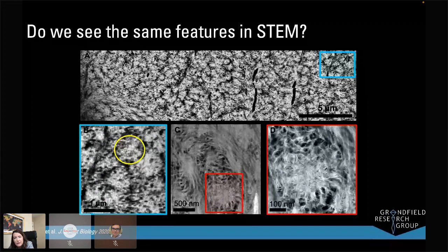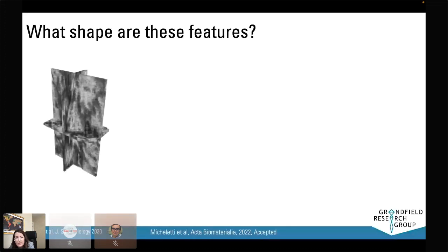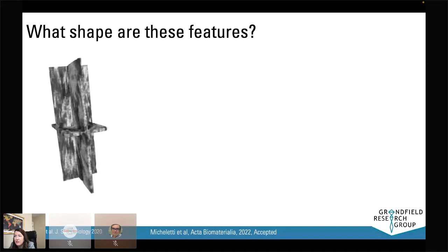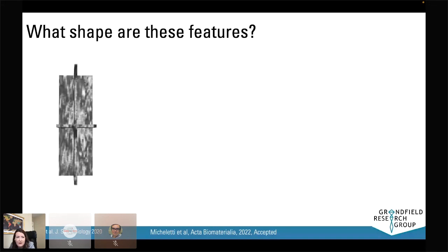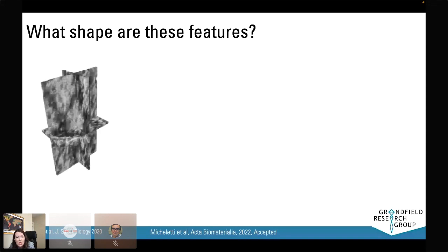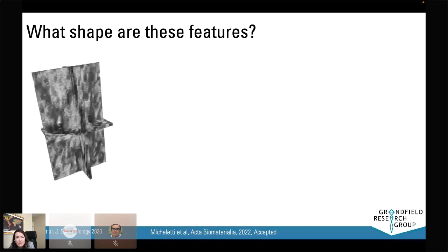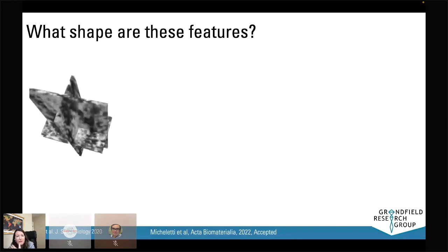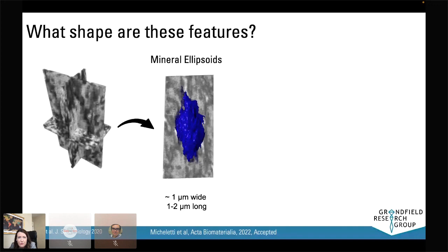So these features appeared circular in the TEM, but now with the plasma FIB, we can explore what shape they actually are. When we look at the three-dimensional shape of these features, we find that they're not just circular. They have a circular cross-section in one direction, but they're actually elongated ellipsoidal features. You can see that circular cross-section looking down from the top, but from the side view we see that we actually have a mineral ellipsoid.